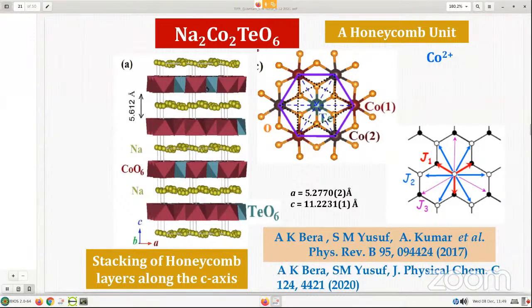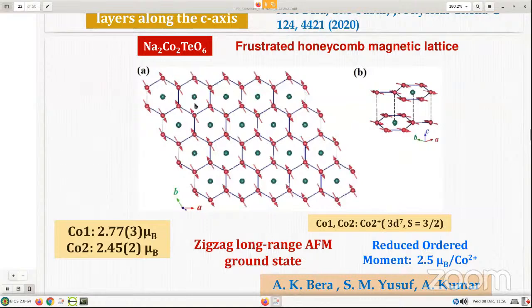This is the crystal structure we have determined, and the magnetic structure also we have determined. There are two crystallographically inequivalent cobalt sites, cobalt 1 and cobalt 2, but forming a honeycomb lattice. If cobalt 2+ behaves as an effective J half system, then it is expected to satisfy this bond dependent exchange. This is our magnetic structure at the ground state, the frustrated honeycomb magnetic lattice, derived by doing powder neutron diffraction.